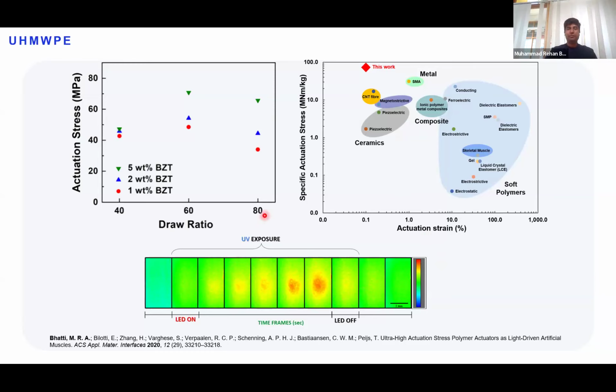Following the results shown here, however, it was found that the actuation stress as a function of draw ratio exhibits an optimum. We were hoping that if we keep on increasing the draw ratio or the chain orientation, the Young's modulus would keep increasing. Yes, the Young's modulus is increasing, but the negative coefficient of thermal expansion is decreasing because more and more chains are being straightened, and they are showing less relaxation within their chain strength. So we got the optimum, but we needed some explanation of what happened and why this was the case.